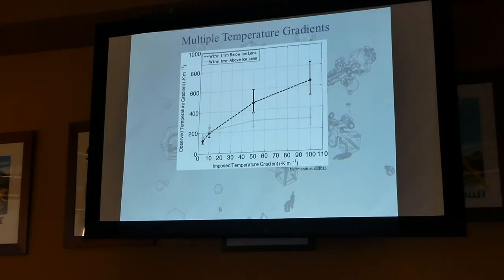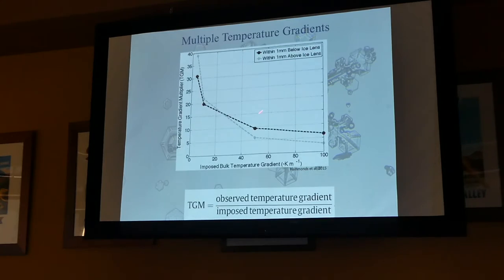And another way to look at that, which I think is more intuitive, is not just how much greater it is, but how much greater it is as we turn down the temperature gradient more to the natural world. So here we looked at 100 C per meter, turned it down to 50 C per meter, down to 10 C per meter, which is kind of the magic number, right? And then down to 4 C per meter. And what we saw was that even when we get to 10 C per meter or below, we were still seeing really large temperature gradients occurring at that interface. This would be something you'd never be able to measure in the field, at least not with your standard equipment, but it was much greater.